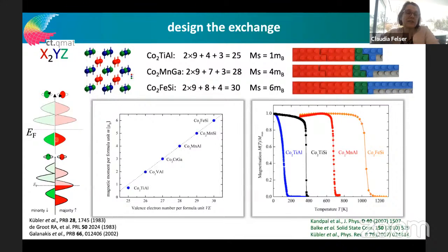For cobalt, manganese, gallium, we have 12 in each spin direction, which means we fill up the closed shell electrons. These are 24 electrons. And then we have 4 electrons on top, because 28 minus 24 is 4 electrons. And this is exactly what we measure as the saturation magnetization in this compound. These are exactly the leftover electrons in this half metallic ferromagnet, which is semiconducting in one spin direction and metallic in the other spin direction. So these are the 4 electrons, and this is the formula.